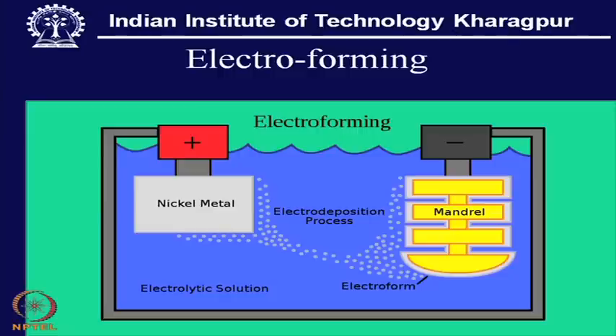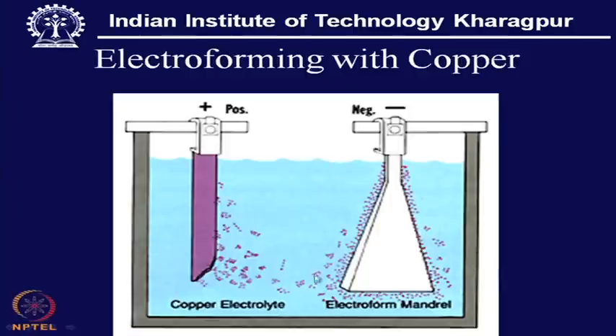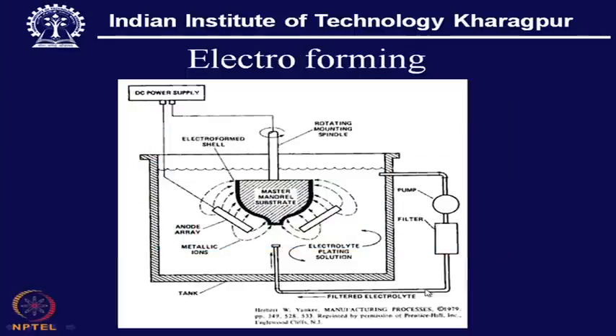Now, here we have some examples of electroforming, that means this electro deposition can also be used for making a form over a substrate, and then this mandrel can be withdrawn and we can have a freestanding shape. So, this electro deposition is not just for covering the metal, but also for getting a freestanding surface. This is another example with a different shape. It is like a taper, and deposition on copper can also be done. This is also an industrial application, electroforming of a vessel, and with this anode array we can have flow of the material, and as a result we can get a very uniform surface